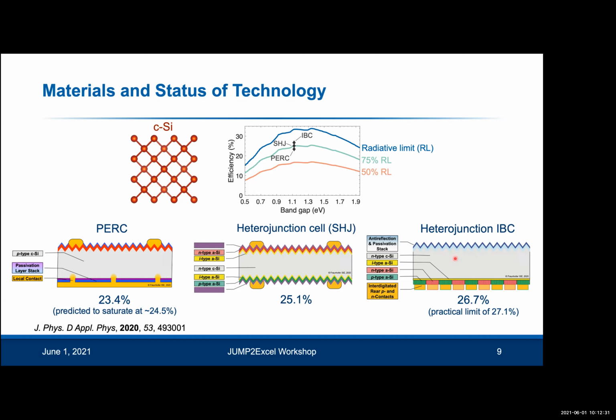But in reality, what people have found is that the most efficient IBC cells actually do use this heterojunction passivation. They do use the amorphous silicon to passivate the front and back surfaces. And that has led to the record efficiency for crystalline silicon under non-concentrated sunlight, which is 26.7%. That's very close to the practical efficiency limit for this device structure of 27.1%. The disadvantage of this structure is that it's more expensive because it's more complex to have this interdigitated back contact structure. So of course, to justify the higher cost, these devices need to have high efficiencies.